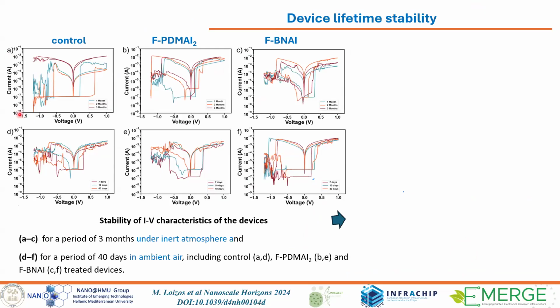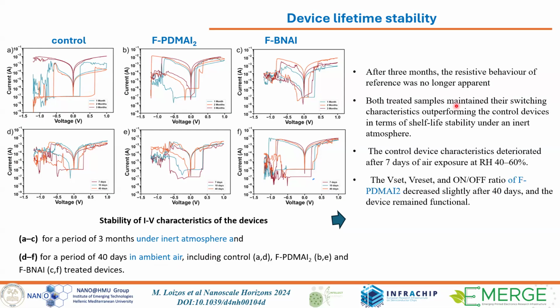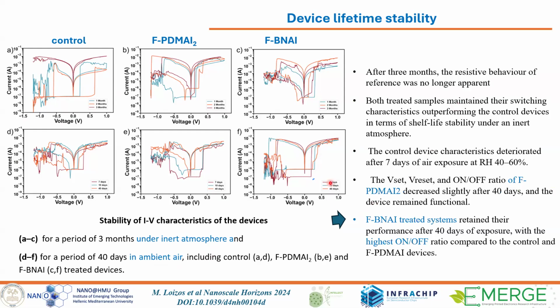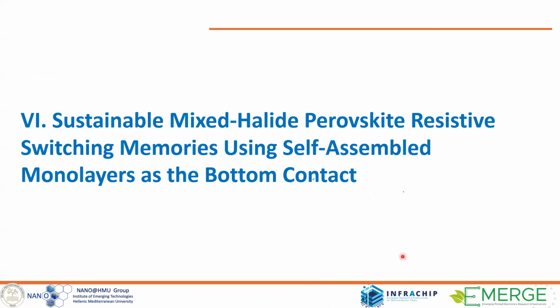And then we monitor the device lifetime stability. For this, in the first row here, we kept the devices in the box under inert atmosphere, and we measure them periodically. And then we put them again back in the box. In the second row here, we have another test. We put the device outside in ambient air without encapsulation, and we monitor again the performance of the device. So to be brief, here again, devices with the capping layers, the 2D perovskites on top, show the better stability, especially BNA, which retained its performance even after 40 days outside the box without encapsulation, giving us the highest ratio compared to the control and to the other 2D capping layer.